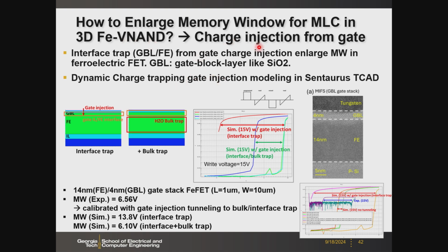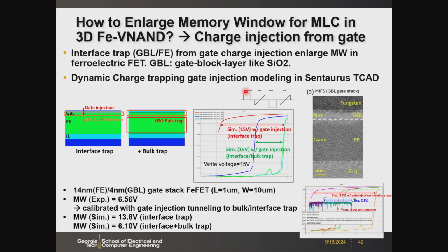Here the idea is to do the gate injection. For the charge trapping, actually it's harmful to the FeFET if the charge trapping comes from the channel side, because for the charge trap transistor, the switching direction is opposite to the Ferro. The Ferro is counterclockwise in terms of ID-VG, and the charge trapping is clockwise. So if you do the charge injection from the gate, those two effects will add up instead of conflicting with each other. The key is that we have to design some interface from the gate side to allow the charge injection into the Ferro. Then we can boost the memory window. For example, in this case, we can create a memory window up to 6 or 7 volts if we have this kind of charge injection layer from the top.